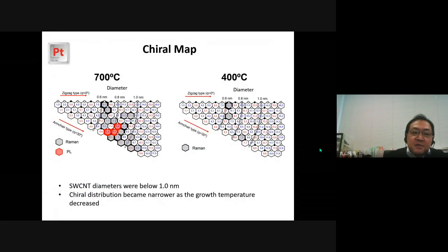We also performed Raman measurements and determined chirality of grown nanotubes. These show the chiral maps of single-wall carbon nanotubes grown from platinum catalysts at 700 and 400 degrees C. Also, both semiconducting and metallic carbon nanotubes are present. The diameters were distributed below 1.0 nanometer. That is, small diameter single-wall carbon nanotubes were grown from platinum catalysts. This would be due to the suppression of aggregation of catalyst particles. As the growth temperature decreased to 400 degrees C, the chiral distribution became narrower and the diameters became smaller. Next slide, please.